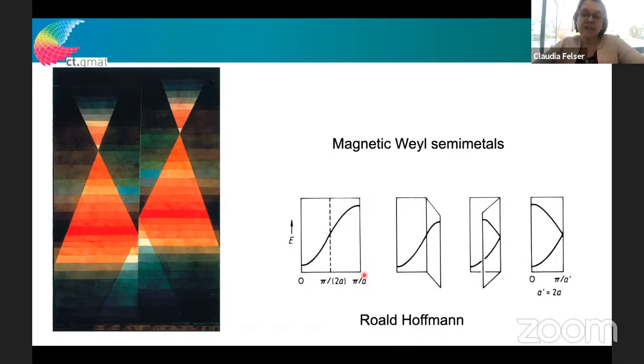So we have this kind of band structure here. And if we have 2 atoms per unit cell, we have to fold back our band structure. Then we end up with this degenerate point here at the Brillouin zone boundary, which means this is not a rare case; these degenerate points are quite common in materials. So it's not surprising that many materials show these features. But you will see that this will have impact even beyond the beauty of topology and writing a nice paper. There might be very, very interesting effects there.